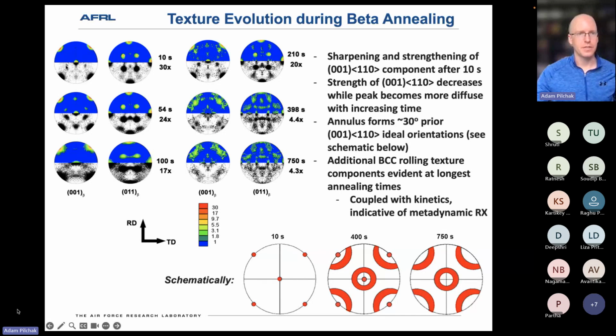And that was important because I think it lets you see some of the subtlety of what's happening in the background, which is too low intensity to actually capture in the probability density representations. So I will first draw your attention to my little schematic on the bottom to try to explain what I observed, and then after that, we can look at the pole figures, and hopefully you'll see the same things here. But as I mentioned, at the shortest annealing times, we had this really sharp texture, very cube-like, or I guess we could call this rotated cube.